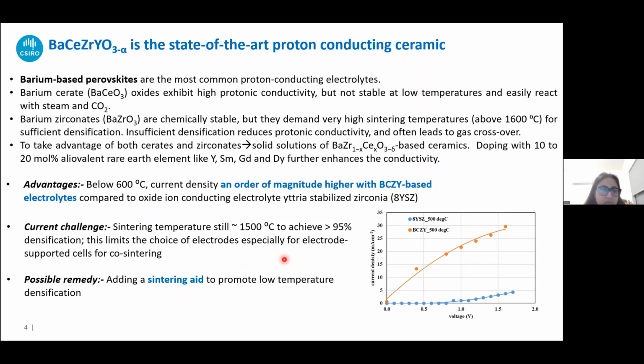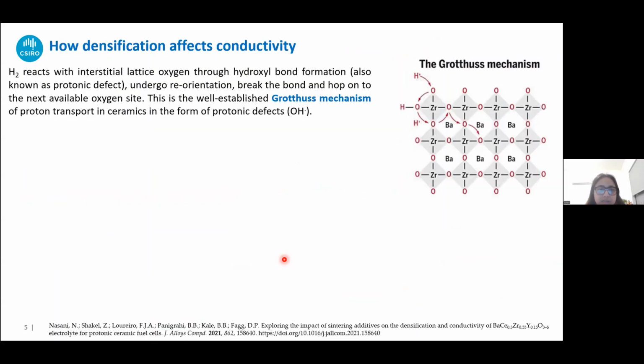Now, before jumping on to what the sintering aid is and how it works, let's see how the densification affects conductivity. In proton conducting materials, the way the protons travel across the electrolyte is via the Grotthuss mechanism. So what happens? The hydrogen reacts with interstitial oxygen through hydroxyl bond formation, as you can see here in this image, and then they undergo reorientation, break the bond, and then hop on to the next site. And then again, they rebond with the oxygen, forming the hydroxyl bond, and this process goes on, and that's how they are conducted.